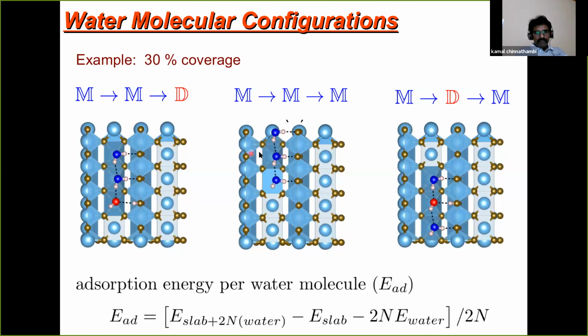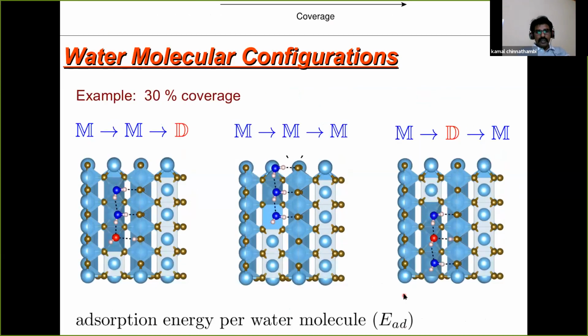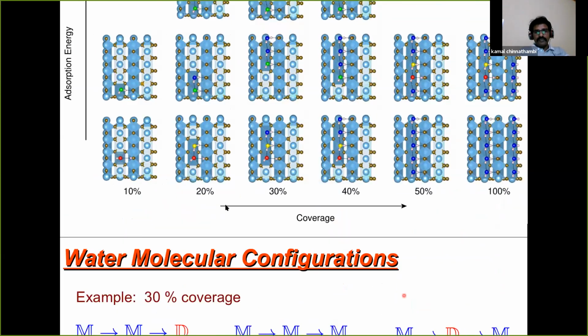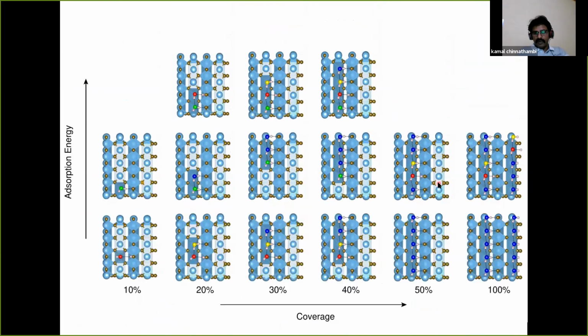After adsorption, we perform the geometry optimization, and then we calculate the adsorption energies. This is the formula we used for calculating the adsorption energies. In this slide I'm showing the different possible combinations we used. I will come to the color coding, why I'm using different colors for the molecules. We used a total of around 15 configurations, and there are around 60 molecules in the system.